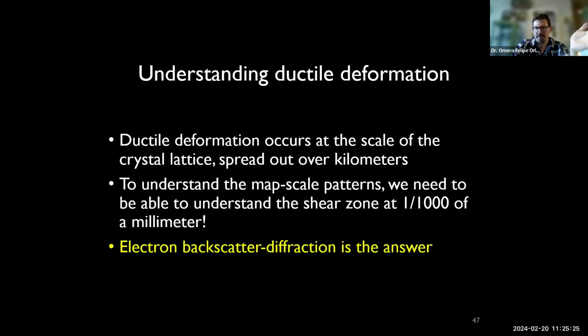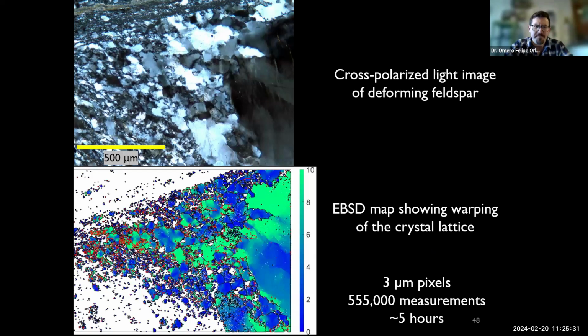So we used one of the coolest things you can do with any electron microscope, and that is electron backscatter diffraction. So here is the same cross-polarized light image that I showed you before, which probably everyone is familiar with because we all had to do petrology at some point. And here is the exact same area of that slide that was polished to within an inch of its life. And then you diffract a bunch of electrons through it by tilting it at a really high angle to the beam in the scanning electron microscope. And then the beam will hit the crystal that has been polished super, super well, and it will diffract through the lattice. And you take a picture of the diffraction pattern. And you can do this really, really fast and in really, really large numbers.